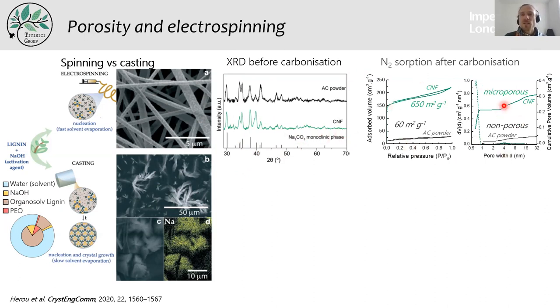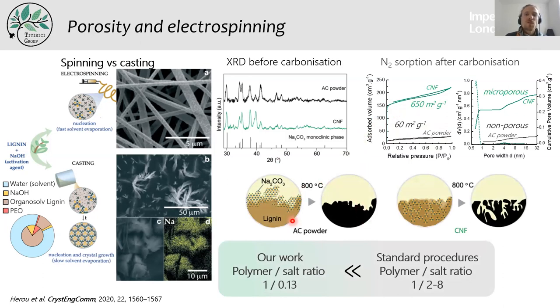And here, if you look at the nitrogen sorption, which tells you the surface area after carbonization, then you can see that the powdered material, so the cast material here, has only 60 square meters per gram, whereas the carbon nanofibers have 650. And that tells you that in the case of the powder, the slow evaporation of the solvent, of the water in this case, is creating a sort of phase separation between the salt and the lignin, and that doesn't lead to high surface area formation. Whereas in the case of fibers, the surface area is very large because since the water evaporates very, very fast during the spinning, the sodium hydroxide doesn't have the time to separate from the lignin, and that leads to really high surface area.